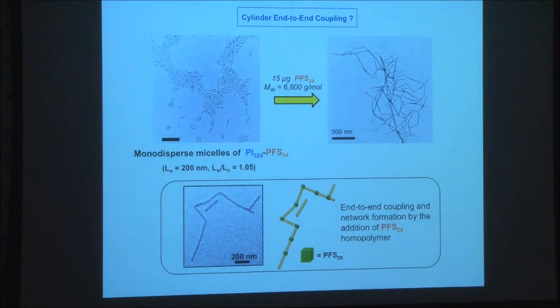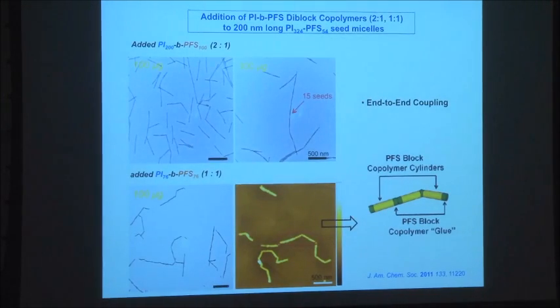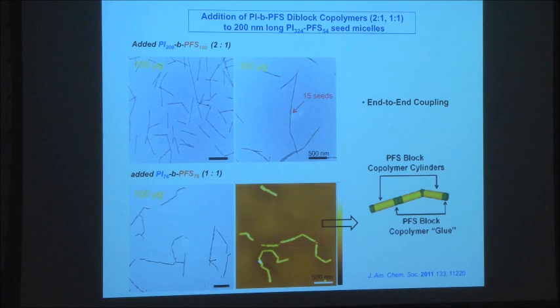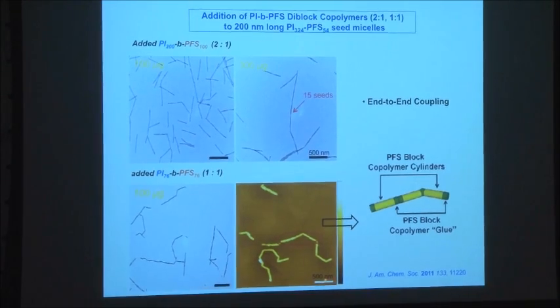You can start growing these structures together, and we've been able to control it to some extent. Here's somewhere we've been able to glue these together, so you can actually join them using homopolymer or block copolymer where you have a very short coronal block. Use these, and you can really start to control it quite nicely. But you have to do it deliberately. Otherwise, as far as we can tell, they're indefinitely stable.